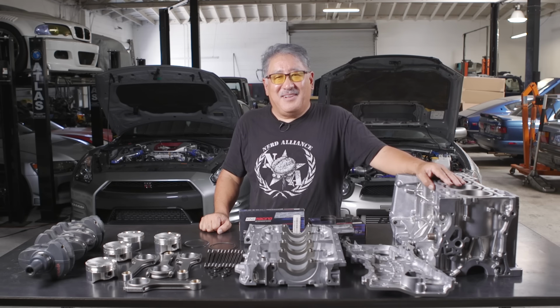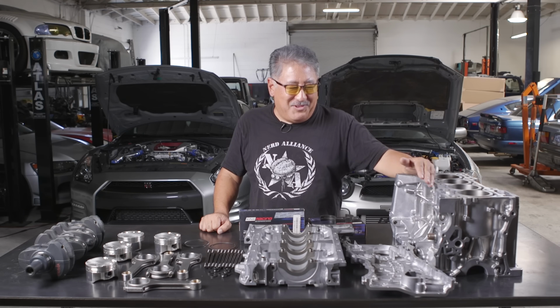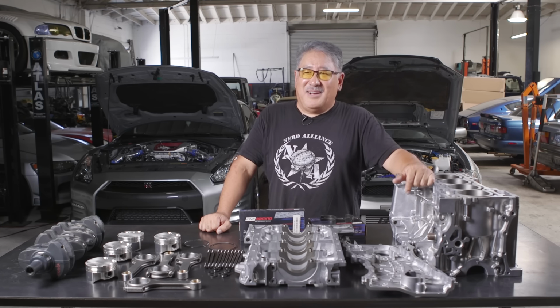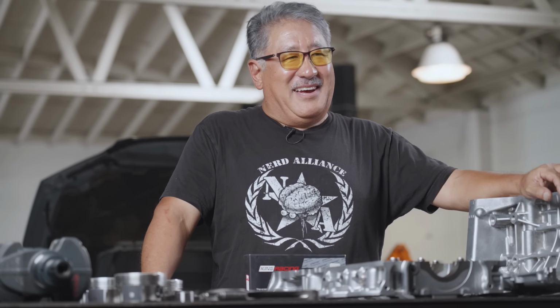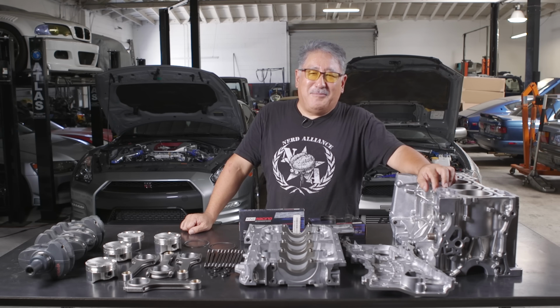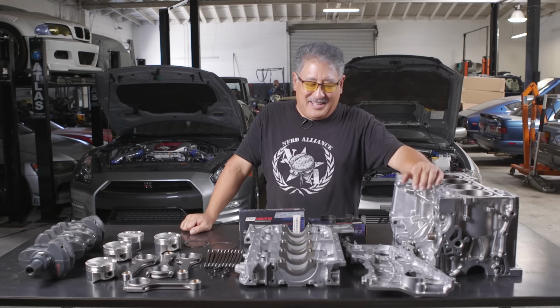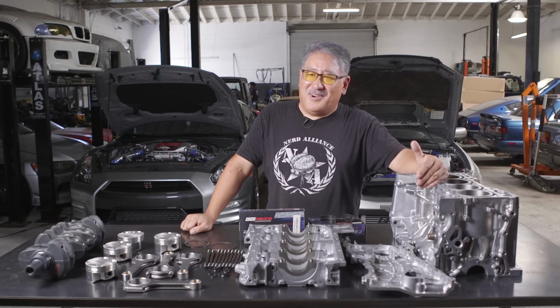Controlling the main bearing clearances is important, especially with modern aluminum block engines. The thing is, the aluminum grows, so the clearance can grow with temperature. If you don't keep those bearing clearances really nice and tight, you can start losing oil pressure. We've seen engines that other people build that have almost zero oil pressure when they're idling and hot, but you won't see that with our motors. We take a lot of time to get the clearance right.